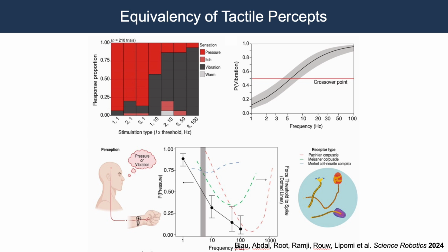And this happens to be right where the crossover point is between where the Merkel cell neurite complex is most active, and that's a low frequency, slow adapting mechanoreceptor that's responsible for feeling the edges of objects and small deformations, to where the Meissner corpuscle is most active, right around 6 hertz and higher, and that is the mechanosensory afferent that is responsible for the sensation of fine texture and low frequency vibration. So we haven't done the microneurography to prove that that's why this crossover is happening, but it certainly seems likely.